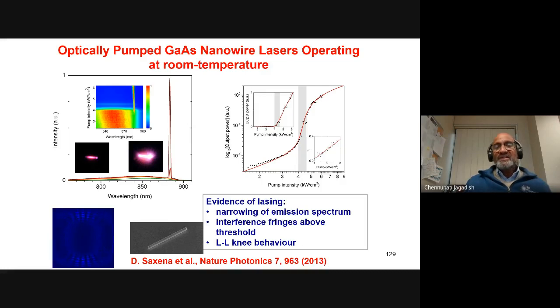Okay. So in fact, these are the first gallium arsenide nanowire lasers operating at room temperature, which we published, and it created a lot of excitement in the community. And just to give an idea, these nanowire lasers are about 6 microns long. So that means I can put about 20 nanowire lasers in the width of your hair. That really tells you these are some of the smallest lasers in the world. Smaller the laser, they consume less energy. Smaller the laser, you can switch it on and off faster. Also, you can pack more lasers next to each other for various applications. So that's why people are really exploring these kinds of small lasers, for example.